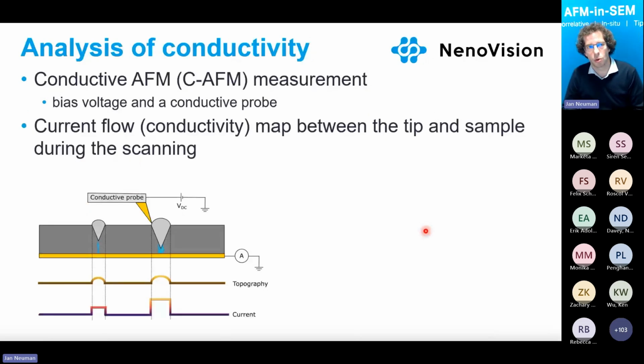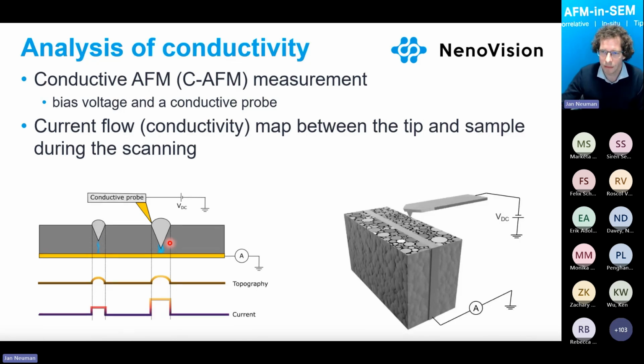We will also do quite a lot of analysis of conductivity. For that, we will use a conductive AFM, which works in a pretty simple way. We use a conductive AFM probe, we bias the tip or the sample, and then we measure the current. Because we are scanning during the measurements, we are collecting conductivity maps. This is the setup you will see on the real samples. We have an AFM tip touching the surface, and then we connected the collector, and we are measuring the current flowing in this circuit.